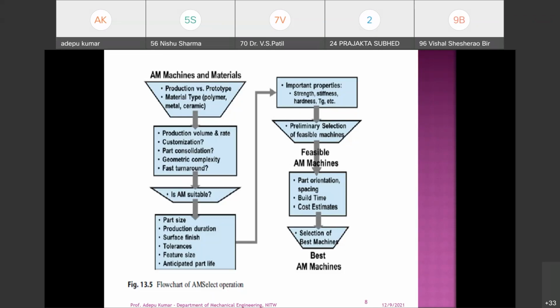So this is based on what previous researchers gave as a solution to us. You should keep a minimum of 1.5 times the thickness. If you keep more, there is no problem, but you are wasting your material. If you keep lower than 1.5 times, the strength comes down. So either way is not useful; the best solution is 1.5 times the thickness. So like that, how much spacing you are giving? If you are giving 1.5 times, that is overlapping.